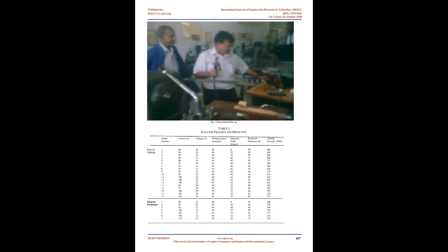2. Experimentation. The mild steel plates of 6 mm thickness were cut into the required dimension, 150 mm x 50 mm, by oxy-fuel cutting and grinding. The initial joint configuration was obtained by securing the plates in position using tack welding. Single V-butt joint configuration was used to fabricate the joints using shielded metal arc welding process. All the necessary care was taken to avoid the joint distortion, and the joints were made by applying clamping stitches.